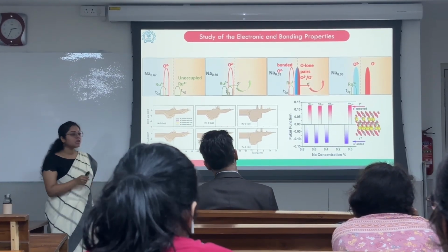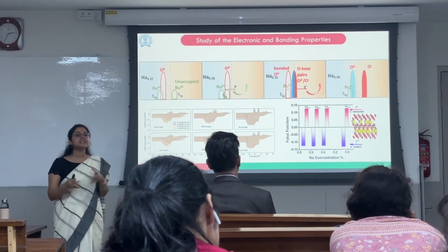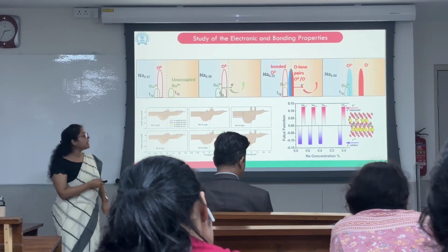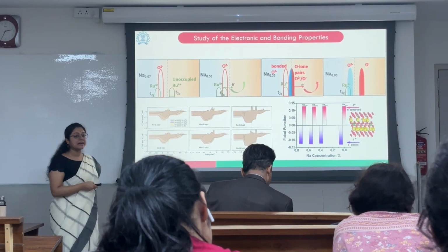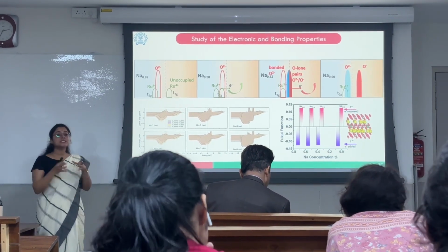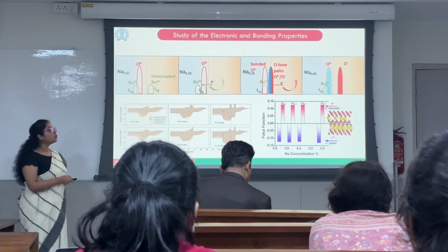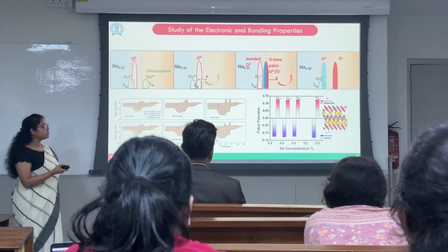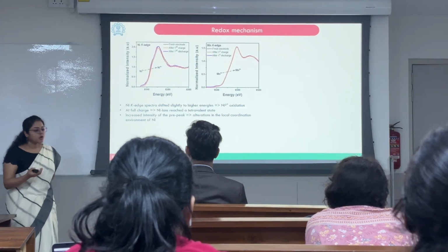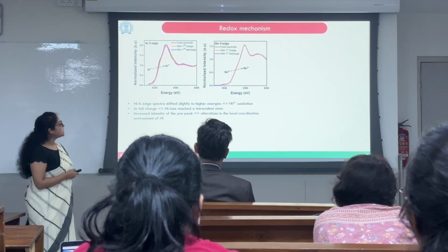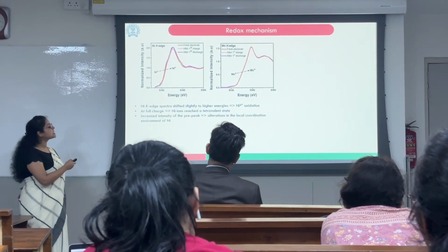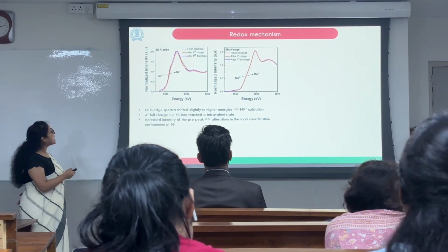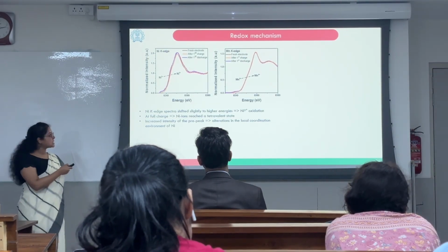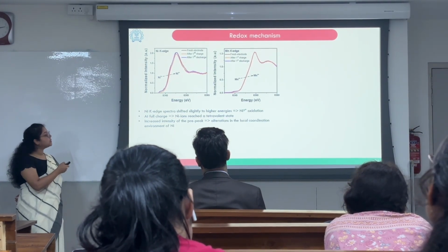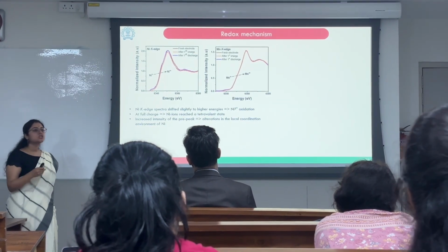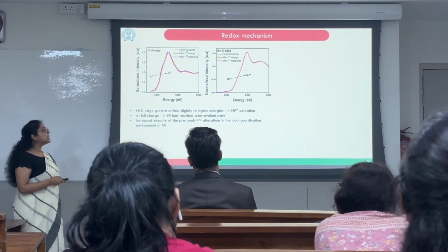So using the Fukui functions, we tried to figure out the chemical reactivity of ruthenium when an electron is removed and when an electron is added. We observed that ruthenium still stabilizes the entire structure when the electron is added or removed. We also studied the redox mechanism through XANES analysis and observed that nickel is the electrochemically active element, and it was seen to go from the 2 plus to the 4 plus state, and the increased intensity of the pre-peak also tells us about the local coordination environment of the nickel.